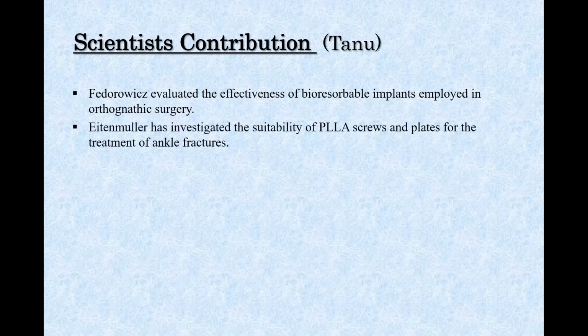Eitenmuller and others investigated the suitability of poly-L-lactide screws and plates for the treatment of ankle fractures. Fractures healed within 6 weeks, but 52% of the patients experienced an aseptic soft tissue problem due to releasing polylactide particles. Prompted by these problems, the authors treated 7 patients with volume-reduced plates and screws with flat heads, and none of the patients experienced any soft tissue reactions. The authors concluded that the use of poly-L-lactide screws and plates is acceptable for the fixation of ankle fractures, and soft tissue inflammatory reactions can be avoided by using implants with reduced volume or biodegradable material.